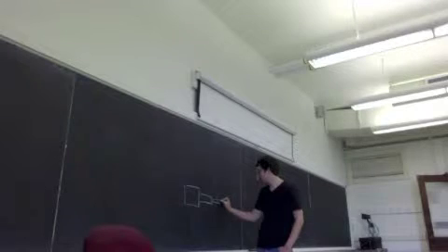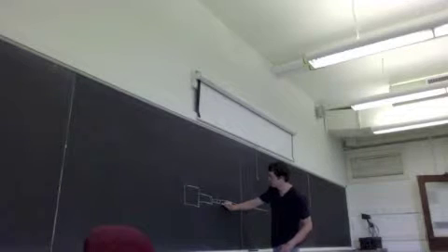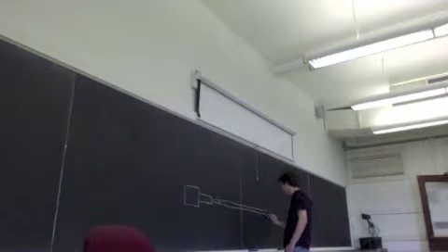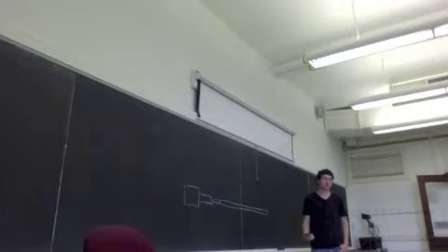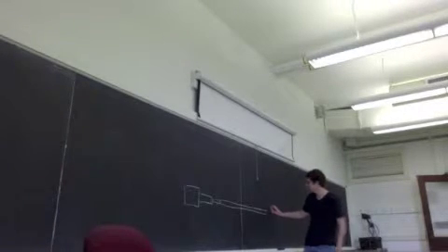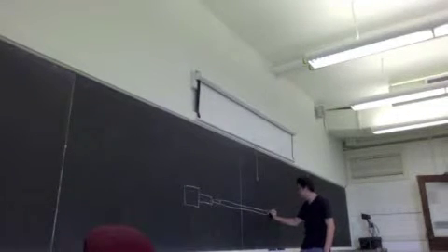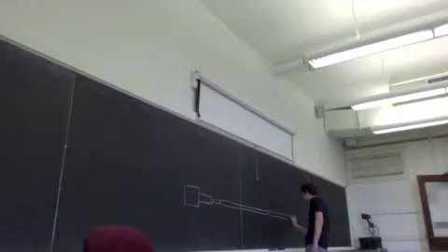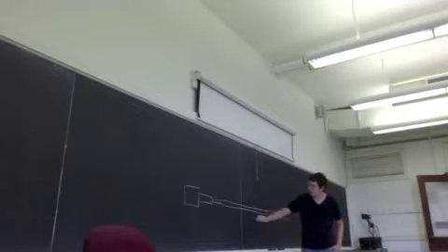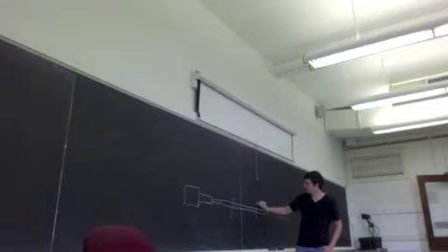Now, what this bar impacts is another long steel bar. And these bars are made of very hard steel. Though you can use other materials if you want, if you want to test very hard materials, such as, again, armor ceramics that the military might be interested in, you want to make a material for your bars that can hold up to the stresses involved. Finally, you put your sample somewhere in here, and then you add another bar. These bars are generally supported carefully with towers along the length so they don't bend, because it's very important that these bars be straight and properly aligned.